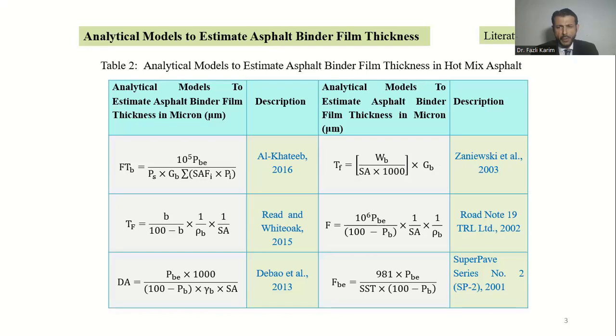And to my knowledge, the asphalt binder film thickness has not been studied at micro level. The effect of temperature and binder content has not yet been calculated at micro level. Therefore, the current study was basically aimed at investigating the asphalt binder film thickness at micro level so that the validity of the aforesaid equations can be checked.